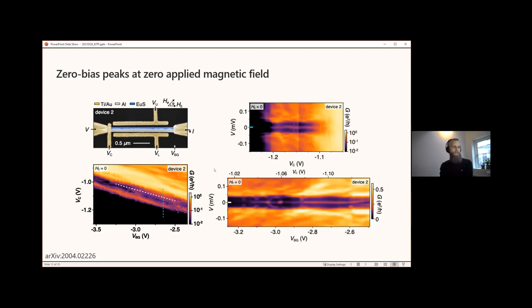If you take another cut in this map, now a compensated back gate sweep, so tuning the charge density in the nanowire, but compensated with the cutter to maintain the same transparency, we find how this zero bias peak forms. And so basically at the more negative side of the back gate voltage, we see spin-split subgap states at finite energy that coalesce to zero energy as the back gate voltage is swept, remain at zero energy for half a volt or so, and then split again.